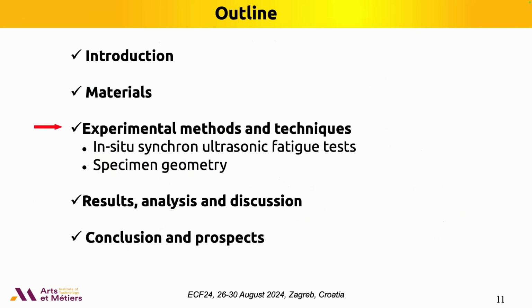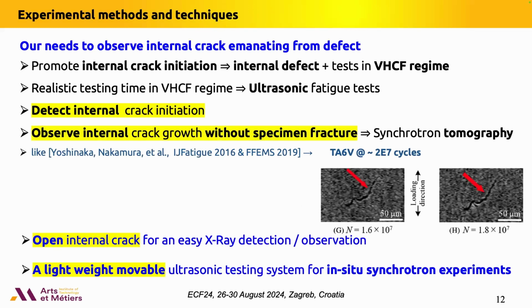So now I'm presenting the experimental method and the techniques. In order to observe the crack initiation, we will use an in situ fatigue experiment with synchrotron. And I'm presenting also the specificity about the specimen geometry. So our needs in order to be able to observe the crack initiation and the early crack growth are the following. I explained that we want to be focused on internal crack initiation. So we have introduced artificial defects and we test in the very high cycle fatigue regime because we know that in this case, we have the maximum chance to observe internal cracks.